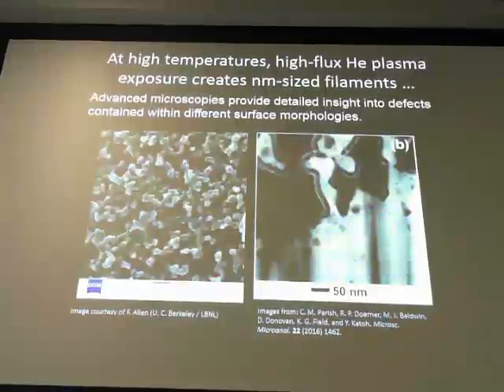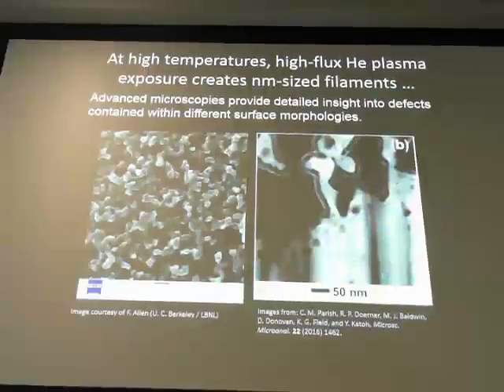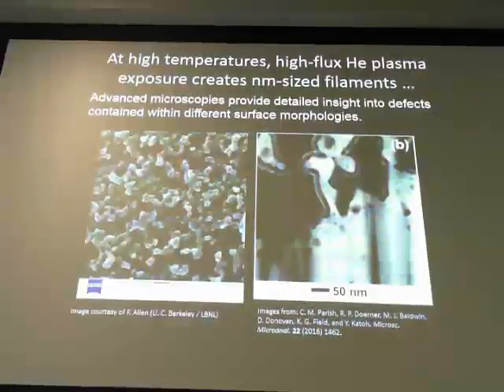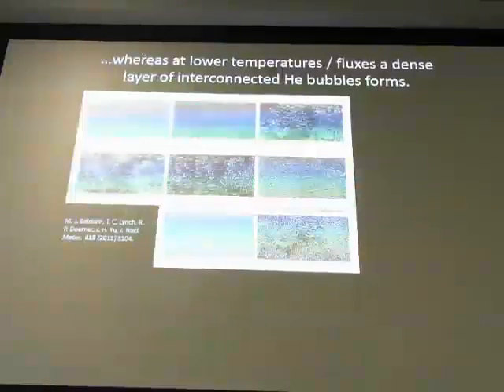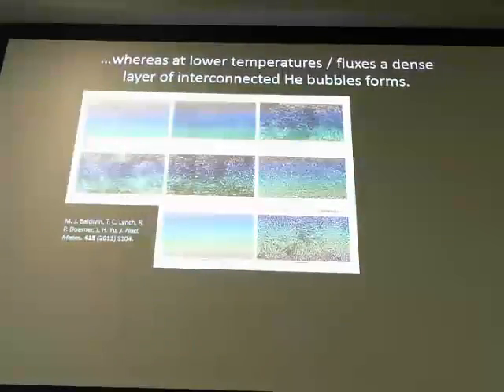I mean, it does depend on... Well, actually, this phenomenon doesn't depend so much on surface preparation. The blistering effect can depend on how the material is prepared, but at least for this coral structure, it seems independent of surface preparation and also independent of microstructure as well. So I will show at least here what the initial nucleation of this type of effect looks like.